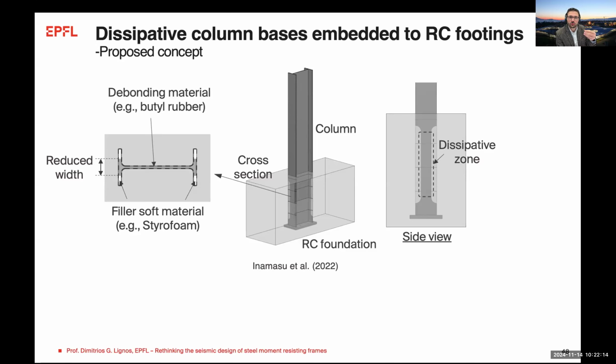But if you don't use rate independent plasticity, which is what we are using, and you use a material law that considers rate dependency, that should be no problem to capture this. Now, how does this influence the overall structural behavior? This we haven't looked at, but that's certainly something worth looking at.